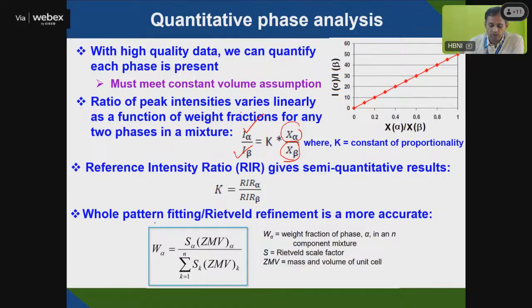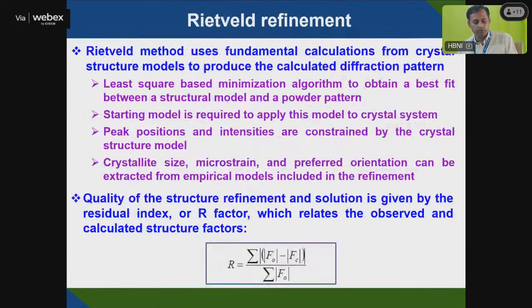So it is linearly proportional to the weight fraction of the individual phase. And if you have a reference intensity ratio, with a proper reference material, you can draw a linear curve, and then you can quantify each phase by using this X-ray diffraction technique. Okay, so for the whole pattern, the Rietveld refinement will do that. That is the scale factor, the scattering from the summation of polarization, temperature, atomic structure factor, everything, divided by the mass and volume of that element, and you can find out this component.